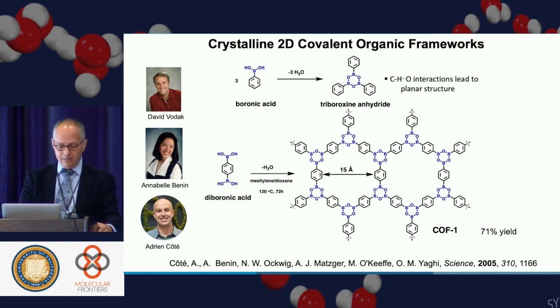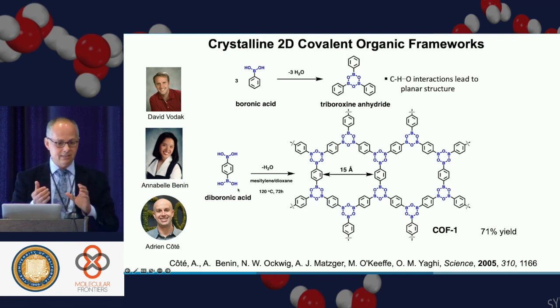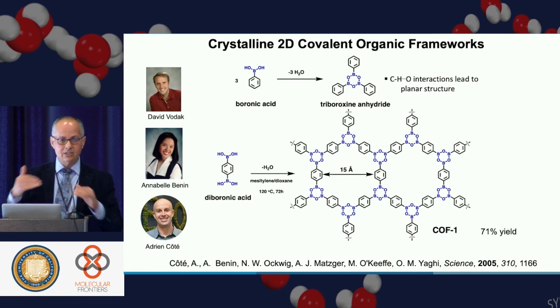But of course, you go to the lab. She went to the lab and she tried it. Of course, she got that hump. But after many different conditions, and what you're doing here, you're not really working in the dark. What you're doing is you're trying to balance the rate of the reaction with the expectation that you need a rate where the molecules can have that microscopic reversibility, that linkage. You can form the linkages and break them. Okay, that's microscopic reversibility. If you don't have that, you're not going to crystallize your material, because if you just bind them together and they cannot break during crystallization, you're not going to make crystals. They will be full of faults and defects.